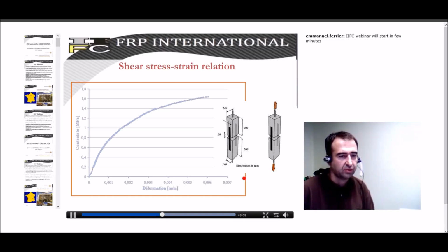For example, if you look at the results obtained with such a test, you have here the average shear stress developed all along the bonding length, and here the strain in the FRP. And as you observe, there is a quite linear behavior. Then debonding starts, and the full failure is then obtained.